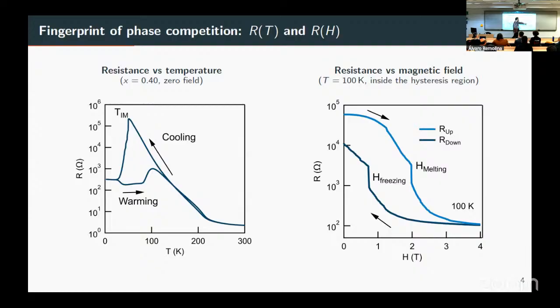For instance, if you notice, there is kind of a jump here, and there are many jumps around. So this is exactly a percolation phenomenon. The jumps follow a power law distribution, and this is also some sort of percolation threshold, but induced by magnetic field. And the reason for that is that, as I said before, these metallic domains are ferromagnetic, and when you apply a magnetic field, part of the phase that is antiferromagnetic converts to a ferromagnetic due to the strong magnetic field, and then the magnetic field drives the antiferromagnetic phase to the low temperature.